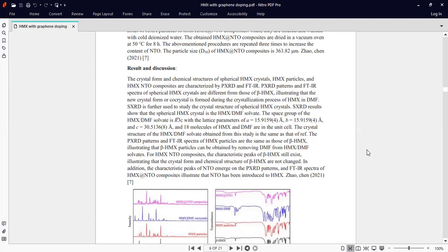SXRD is further used to study the crystal structure of spherical HMX crystals. SXRD result shows that the spherical high melting explosive crystals are high melting explosive DMF solvates. The space group of the HMX DMF solvates is R3C with the lattice parameter of a equal to 15.91594 angstrom, b is 15.9154 angstrom and c is 30.5138 angstrom, and 18 molecules of high melting explosive and DMF are in the unit